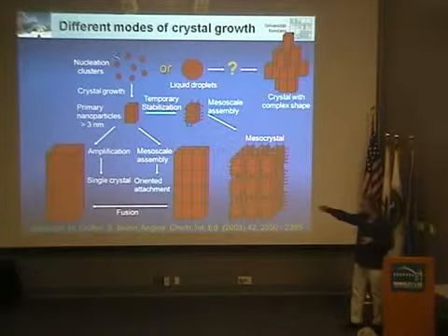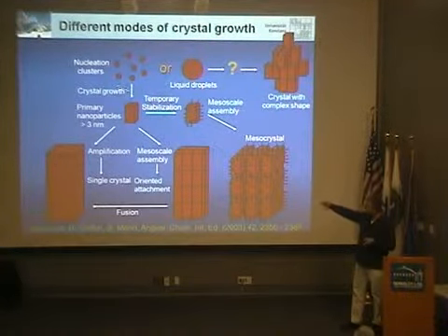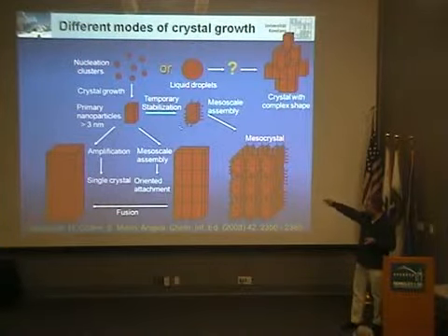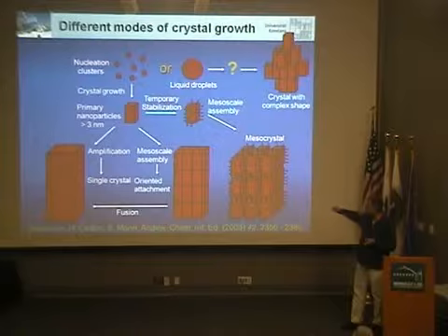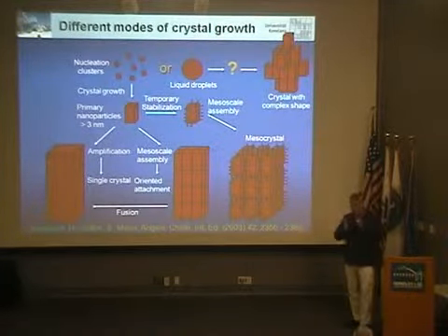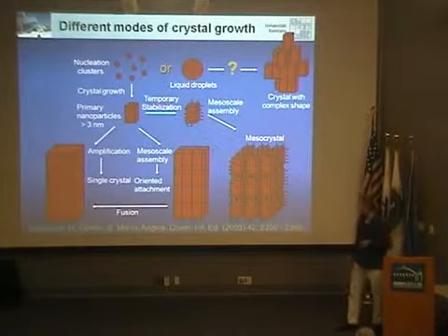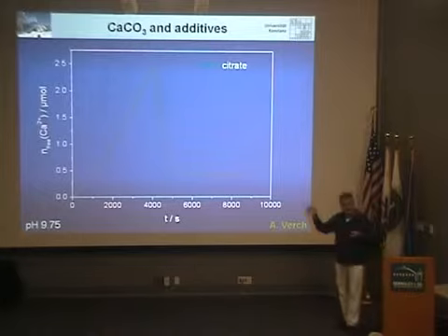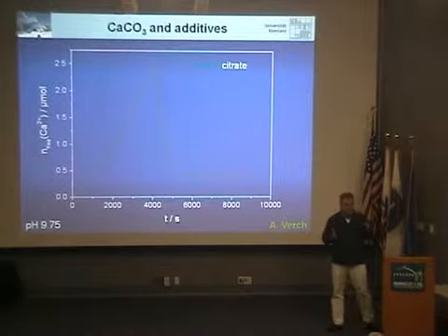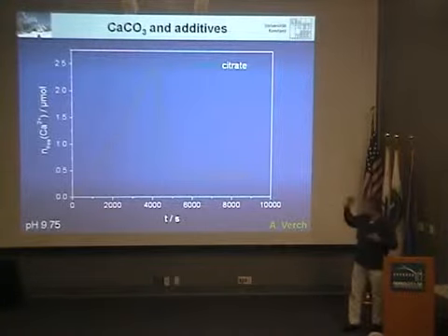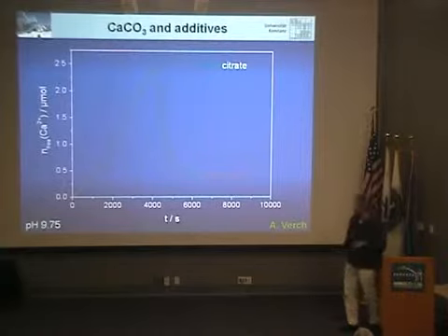And the pathway it goes is that you start to go from nucleation clusters via primary nanoparticles, which get stabilized by the polymer and finally form these polycrystalline superstructures with perfectly crystalline aligned nanoparticles. So I just want to flip you through the additives I've just shown you. We have more curves now to show you that additives have a very characteristic profile. And we hope to extract the features and get out the fingerprint regions basically to make predictions in the future.